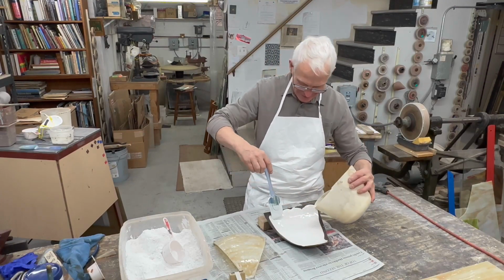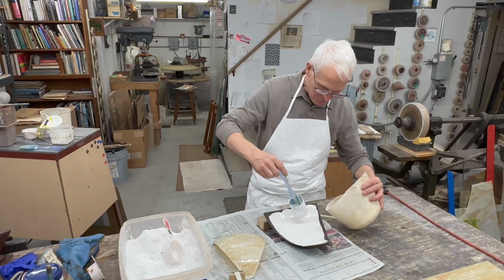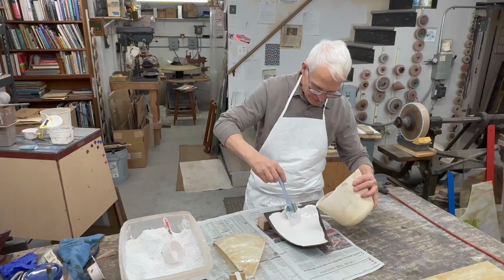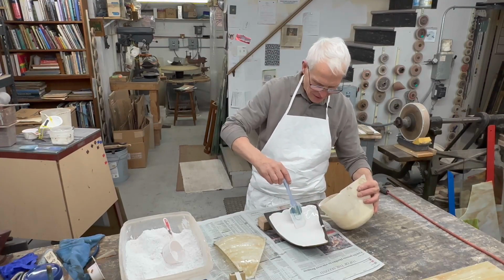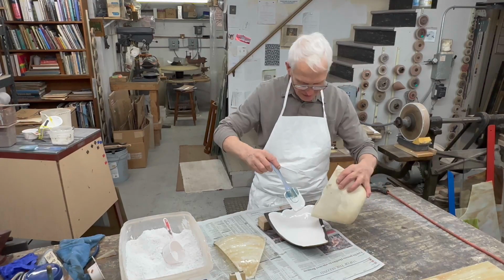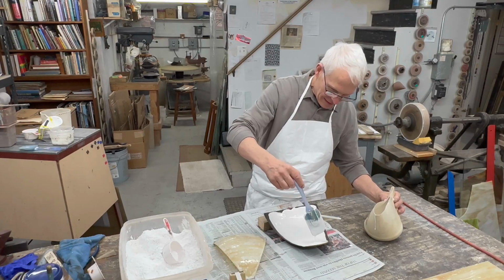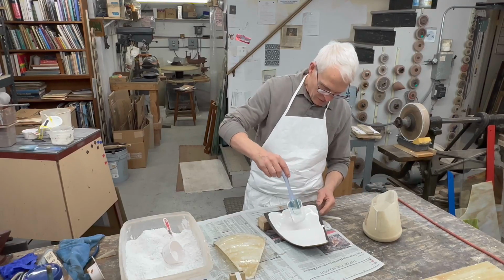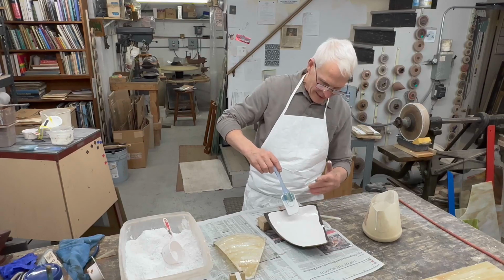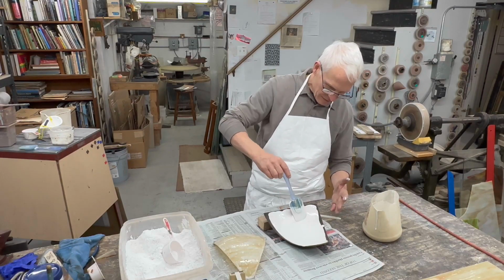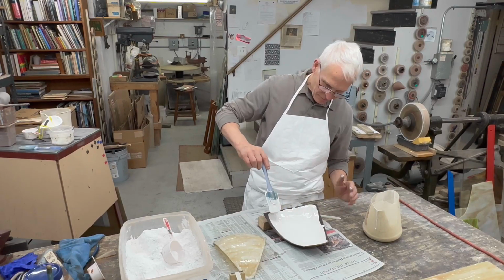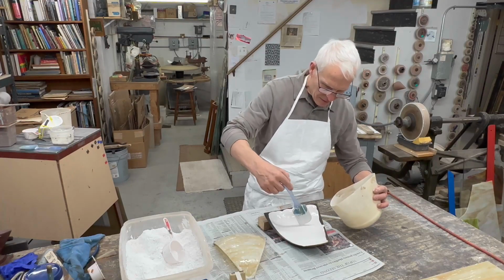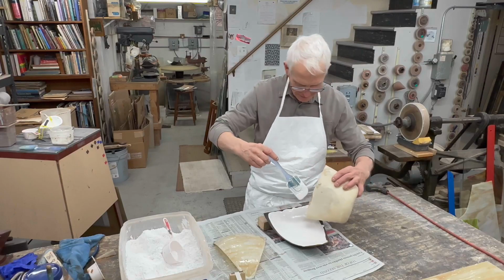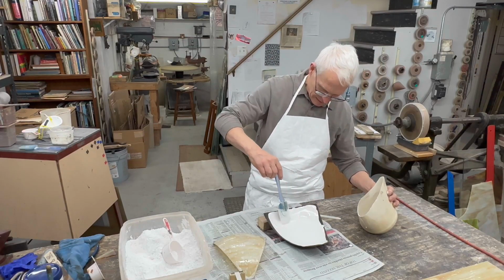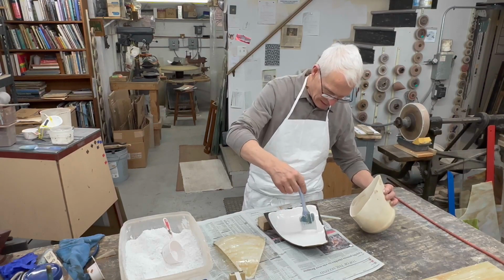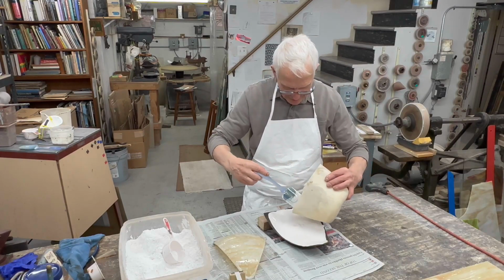So, yeah, you want to catch this where it's just kind of stiffening up, but not too stiff, where you have to press the glass so hard you crack the glass. And in this case, less is not more. You're better off with more, because if you have a void, you can fill it later, it's not a problem, but it's really a whole lot easier if there's enough of this slurry in there to create a really smooth, nice mold. Okay.